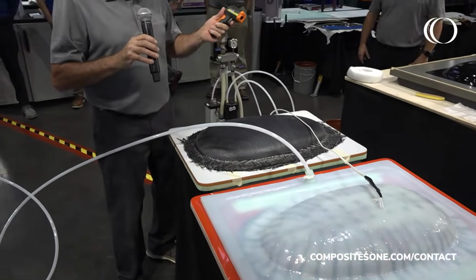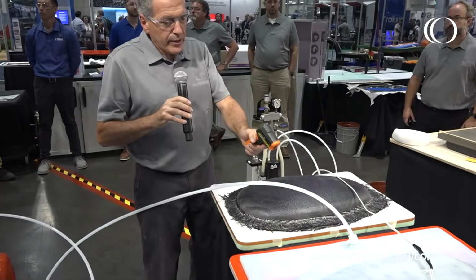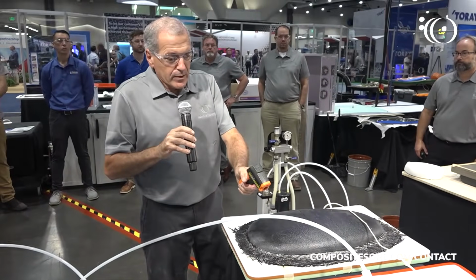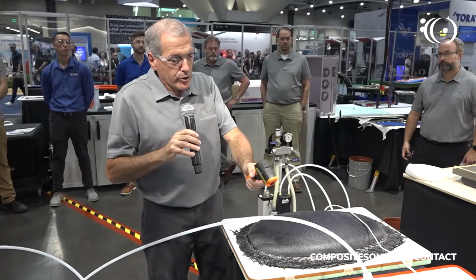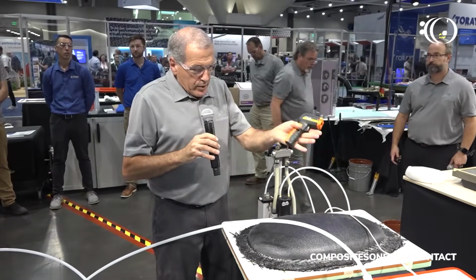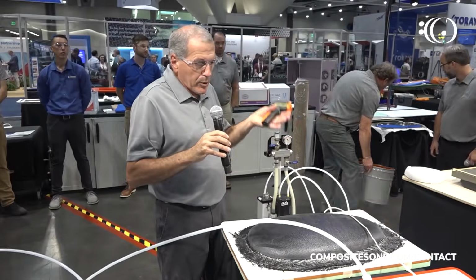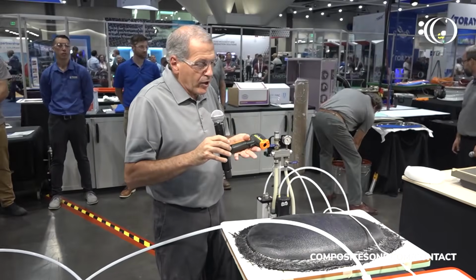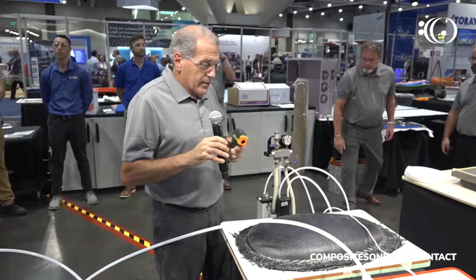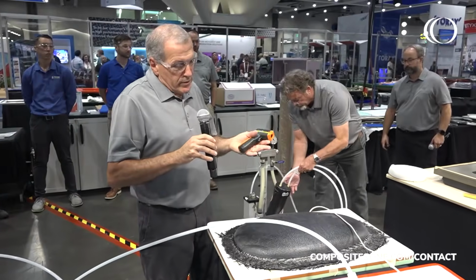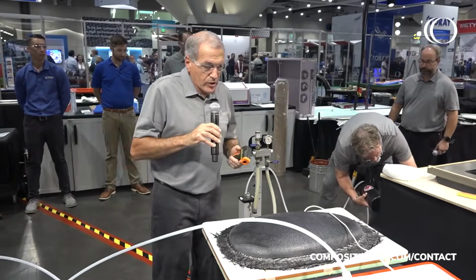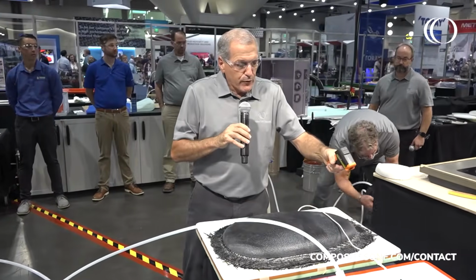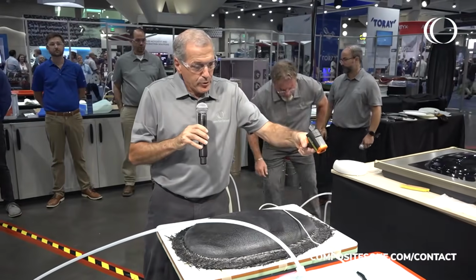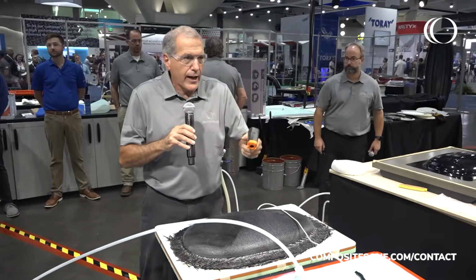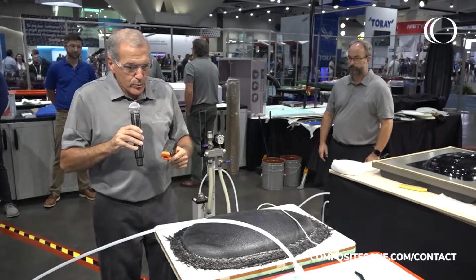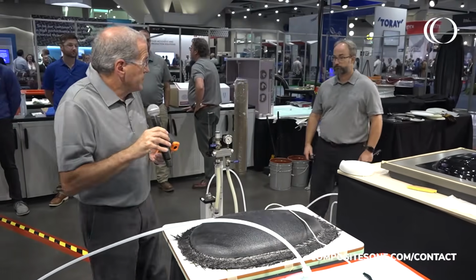This year we decided to try something a little different, so we made a silicone bag with a heating element in it. Right now I'm close to 200 degrees, but we conquer two things with this at once. We're able to put the bag on, pull vacuum on it, and consolidate all of our material. Then we can put the heat to the bag and melt the glue. Hence, we'll have a preform when this is all said and done. So we're heating up. We're going to leave this on for a few minutes longer, and then we're going to be able to turn the temperature down and let the bag cool off. We'll leave it under vacuum through the demo and pull the preform off at the end of the demonstration.